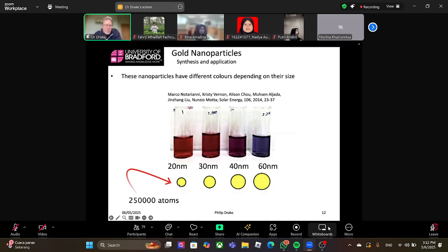So a 20 nanometer particle has around 250,000 gold atoms. So it's a lot of atoms in there. The 60 nanometer particle has about 7 million atoms. So it is a lot of gold metal with a gold surface.